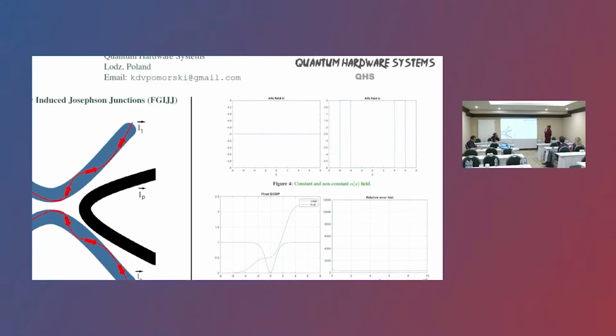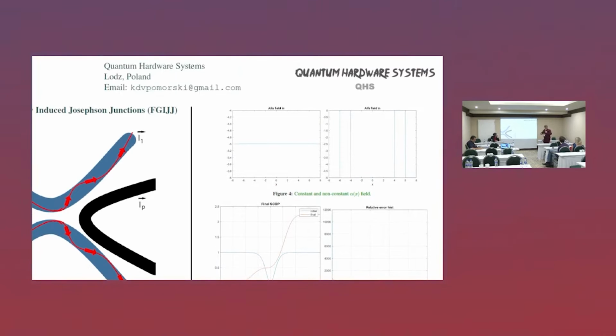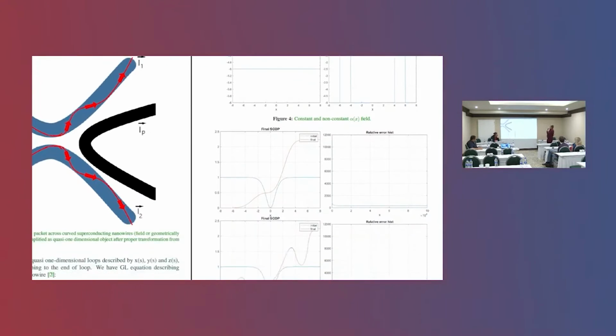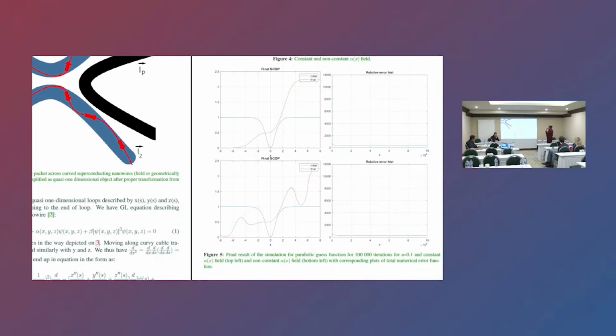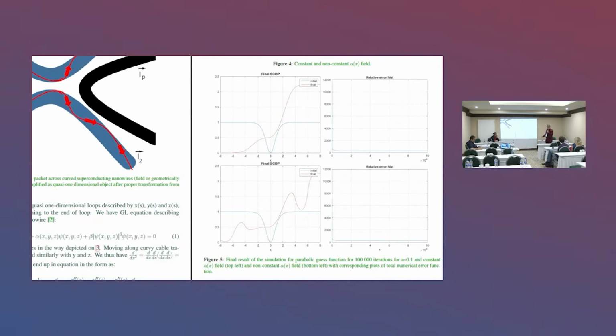Yeah. So we can have alpha coefficient. So we take a cable that is straight. It has alpha coefficient as given here, or has two defects like normal metal in between. So we can bend it, and then let's go a little bit downward. Excuse me. Yeah, go down. Yeah. So then we use relaxation algorithm that minimizes free energy functional, and for those two cases we get distribution which is in red of superconducting order parameter.